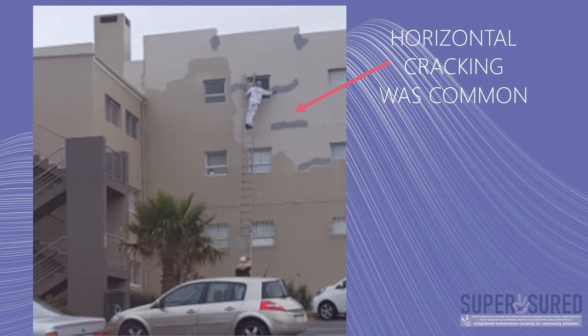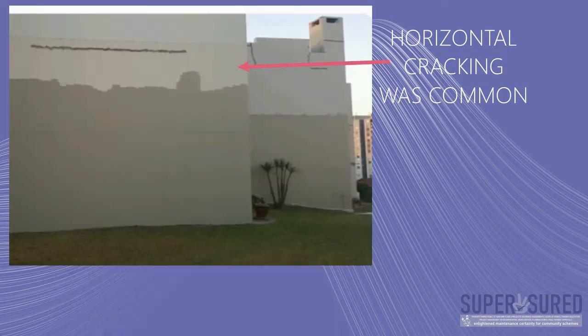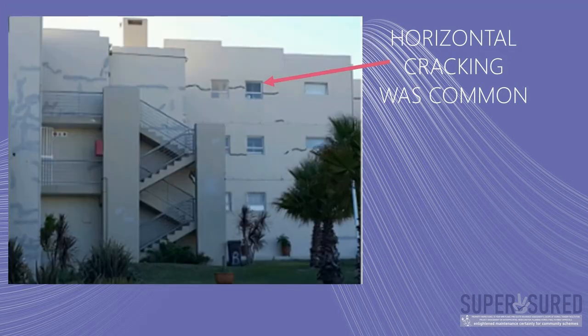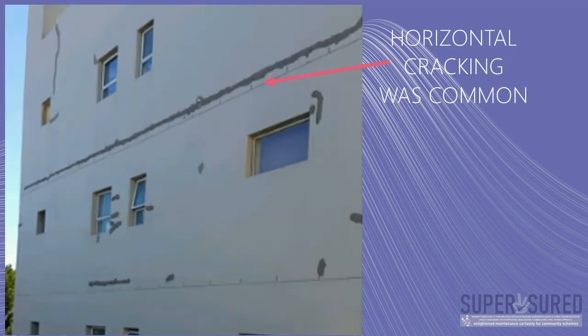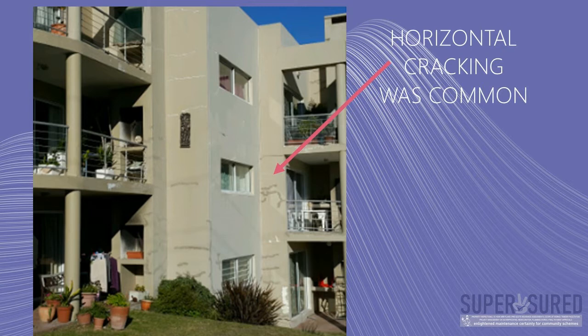Now, in the case of Balmoral, the building is actually built on practically sea sand. And unfortunately, when a lot of the bricks and mortar were mixed, we believe that there was sea sand in there because we saw leachings, white salts that were coming out. We call this efflorescence, but it's the leaching of the salt, which is often common when proper building sand wasn't used, where there was a mix between maybe sea sand. And I think that's what the builder did at that complex. As a result, you'll often find that there's a long section of cracks, which might just be where that particular mortar mix was not done, and you can actually sometimes see the salts coming through.